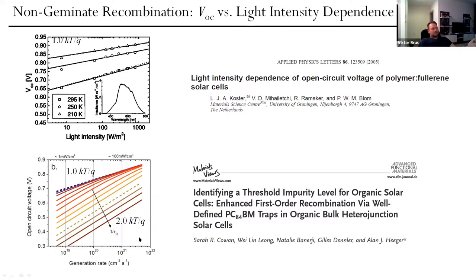We measure JV curves at different light intensities. We use some neutral filters, so we don't change the spectral distribution of our light source. We just put a neutral filter, which reduces equally the intensities of all wavelengths. We measure JV curves, get this VOC plot versus light intensity, and see, okay, if it's one, then we can assume in first approximation that it's only bimolecular recombination.